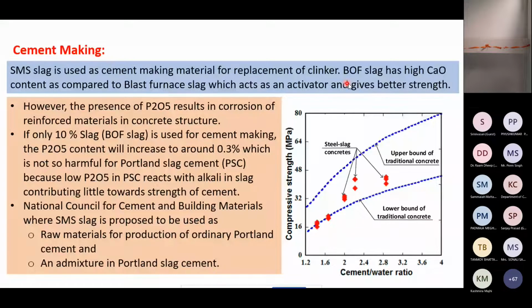Basic oxygen furnace slag acts as an activator and gives the better strength. The presence of phosphorus results in a corrosion of the reinforced material in concrete structure. Now here the main issue is that P2O5 that is present.